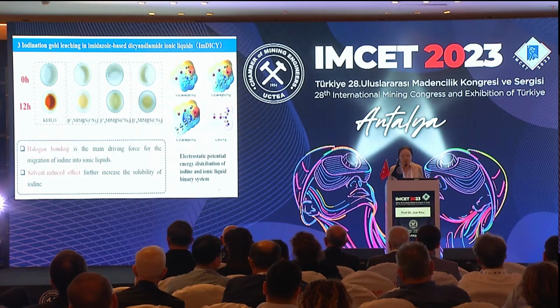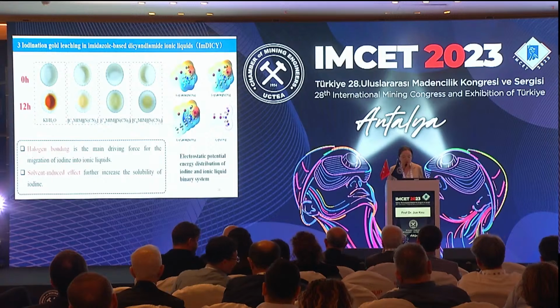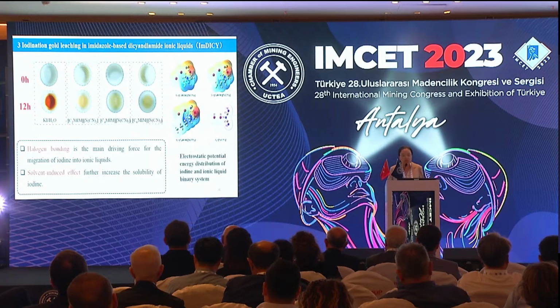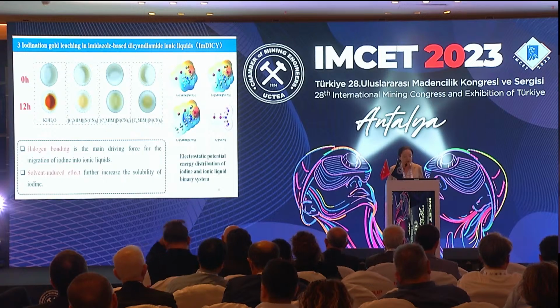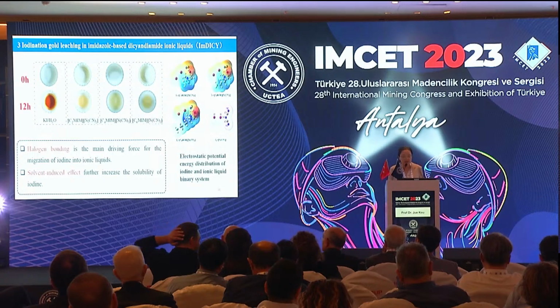We also did the electrostatic potential energy calculation, and we find that the halogen bonding is very strong. It's the main driving force for the migration of iodine into the ionic liquid. And also the solvent-induced effect can further increase the solubility of iodine.